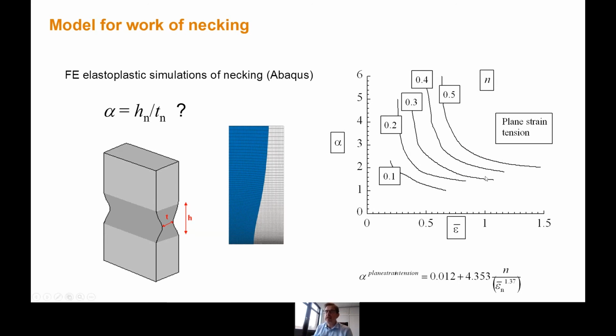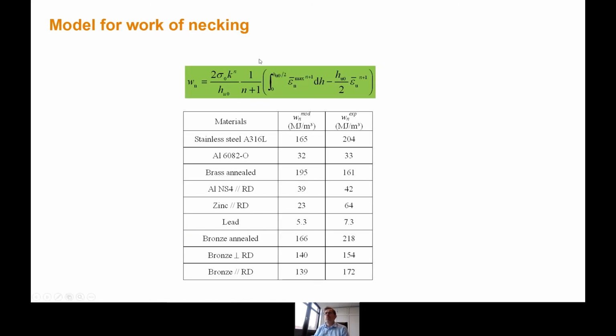But that's important, because that means the higher your strain hardening exponent, the larger the neck. And so more dissipation you can have in your necking zone. And we quantified this alpha parameter running a lot of finite element simulations, and we got even an empirical equation for that. Okay, so we estimated the value of the work of necking from this model, and I'm not going into details, and we compared the prediction with the experimental value. And of course, there is one parameter you're not predicting, but you're measuring, which is the fracture strain. So one of the parameters that enters the calculation of the work of necking is the fracture strain, meaning the strain at which you stop dissipating by necking, because basically it's broken.